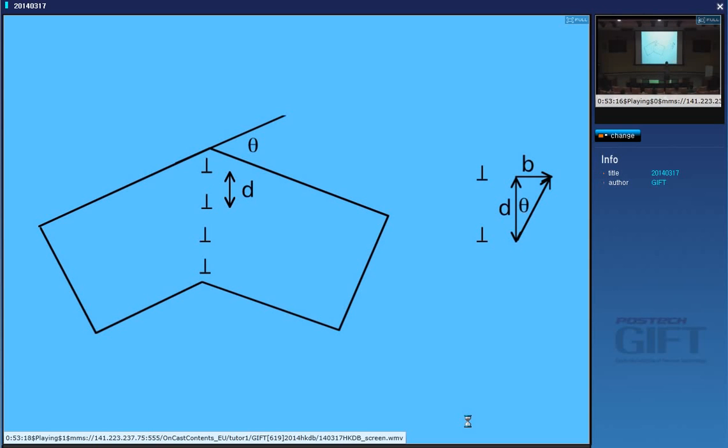So if you look in a transmission electron microscope at an interface, you should see dislocations arranged in a beautiful pattern. Okay? Are you familiar with that? So just look at some images of interfaces in a transmission electron microscope, and you'll see that there are a series of dislocations which accommodate the misfit between the two halves of the crystal. So an interface structure is described in terms of dislocations. This is a very simple interface because basically we've cut a single crystal and we've tilted it like this. But you can tilt like this and like this as well. So in general, you would need three sets of different dislocations to fill that hole which you create, okay? But the idea is that you can completely describe the structure of an interface using dislocations.